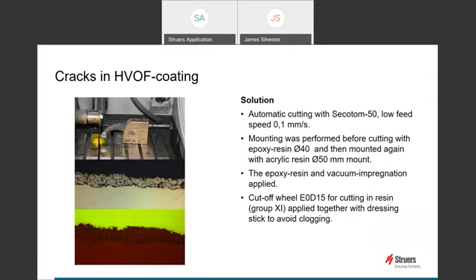After mounting the sample, this choice is removed, as the bulk of the material on a mounted sample, such as this, is now plastic. As such, the best blade option is an electroplated diamond blade. This electroplated diamond blade is designed to cut plastic samples and resist getting the abrasive clogged. In addition, the electroplating should minimize the damage we can expect when cutting the metal. We do need to state, though, that cutting steel with diamond wheels is not desirable under most circumstances.